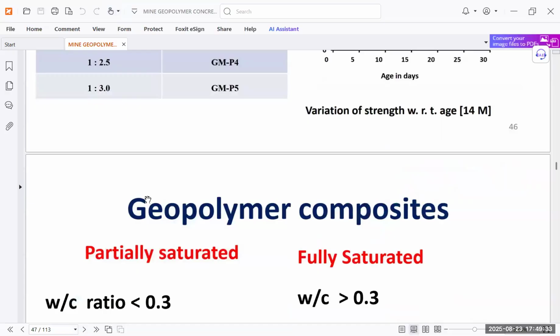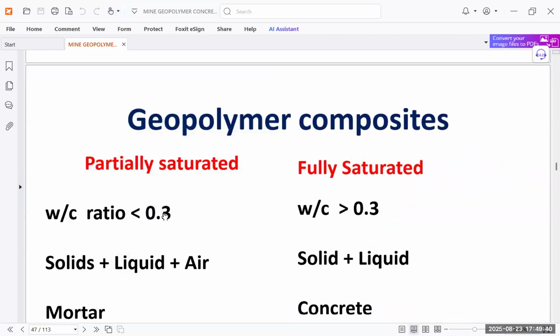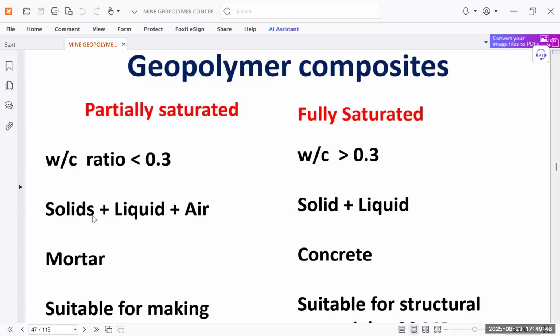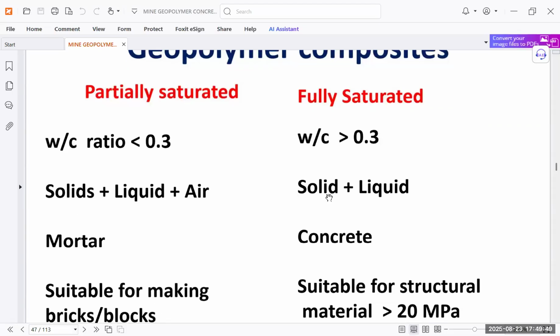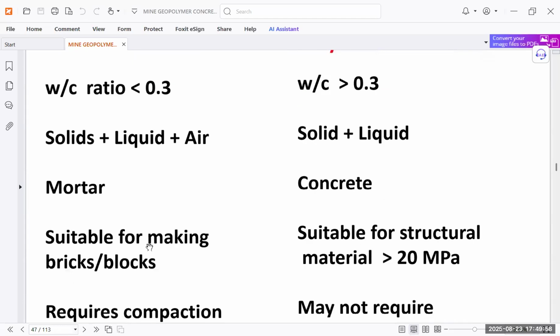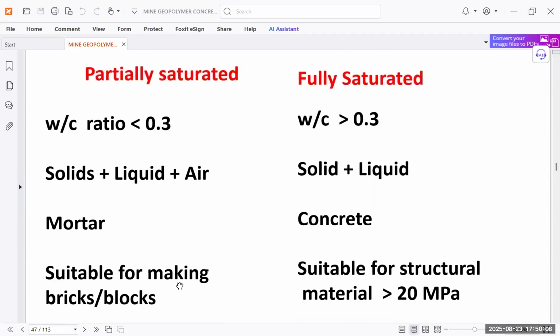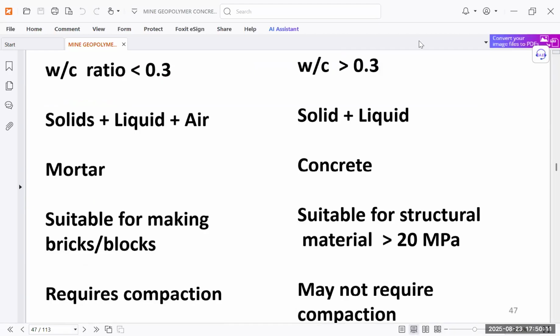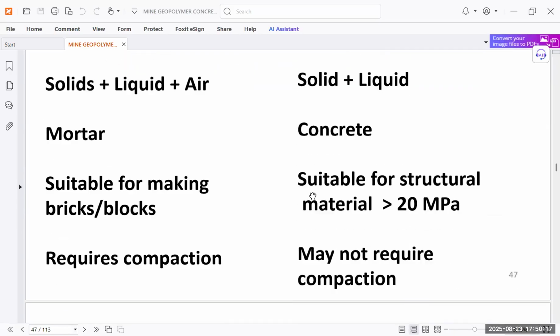For geopolymer composites, we can use water to cement ratio less than 0.3 for partially saturated and greater than 0.3 for fully saturated. Partially saturated has solids, liquid plus air, and fully saturated has solid and liquid only. Partially saturated is called mortar, fully saturated is concrete, and it is suitable for making bricks or blocks, and for making structural materials in which strength greater than 20 megapascal is required. This requires compaction, and it may not require compaction also because here we are not using water, so compaction may not be required. In this case, the W by C ratio is 0.3.